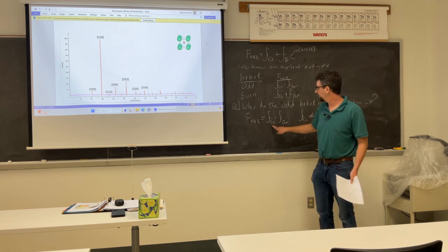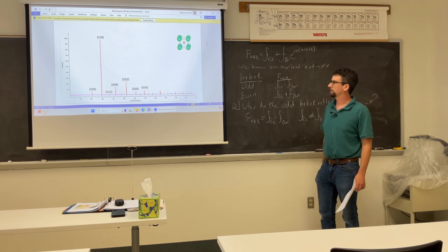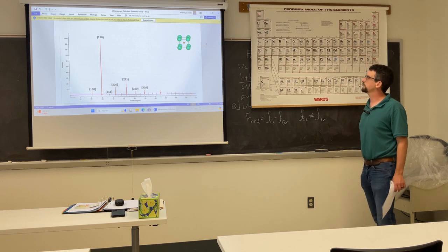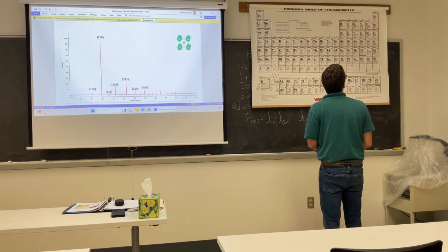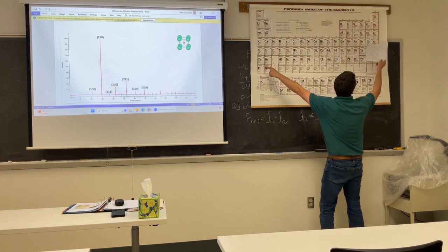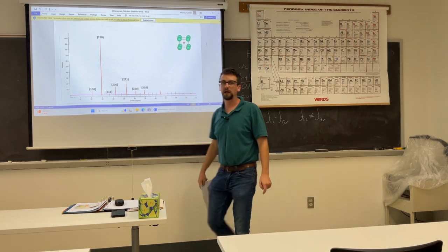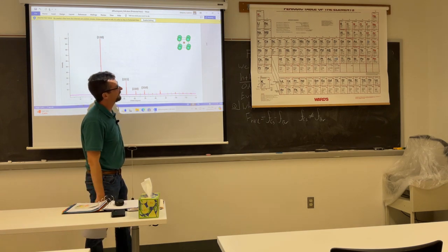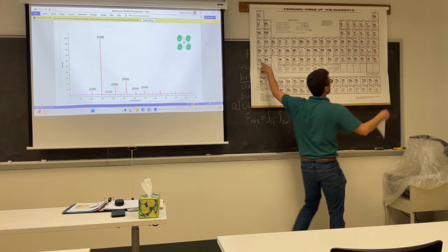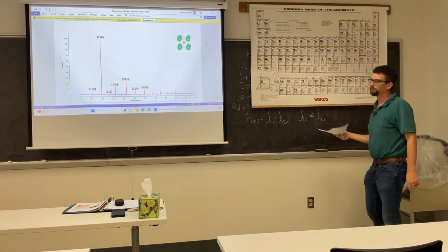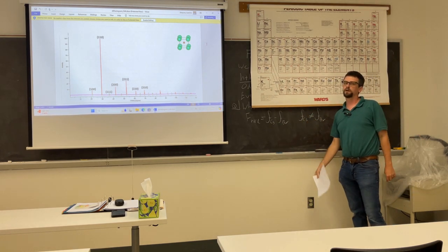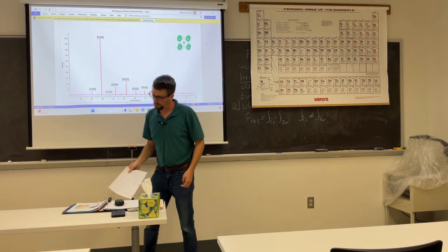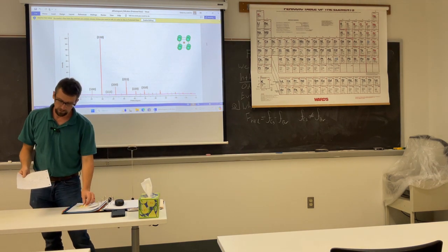Then if we have to compare which atomic scattering factor is larger, if we pull down the periodic table and consider the electron density around these elements, what you can see is cesium has far more electrons, and if you consider its atomic radius, either covalent, ionic, or van der Waals, you will see that it is significantly larger than the bromine. As these two values get closer to one another, however, you will start to see these reflections diminish. So that's what's going on with our cesium bromide example.